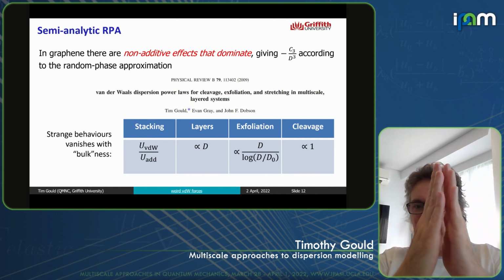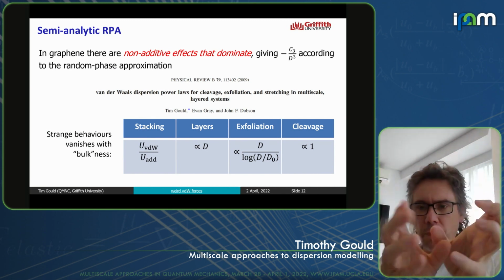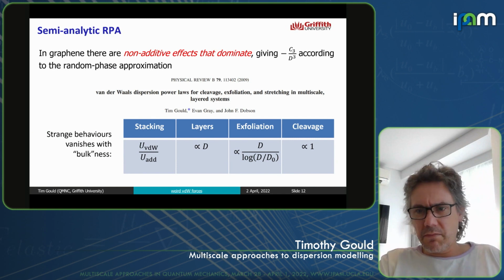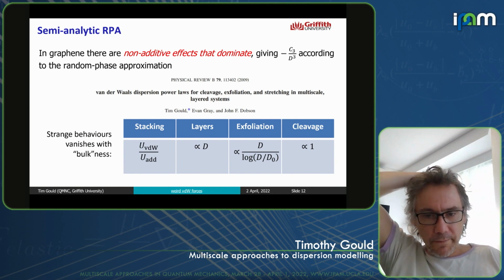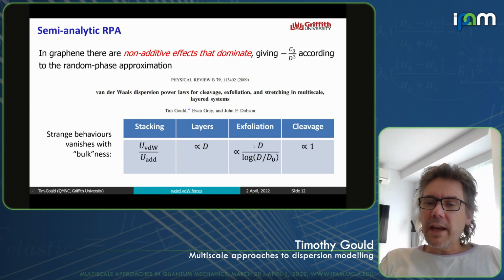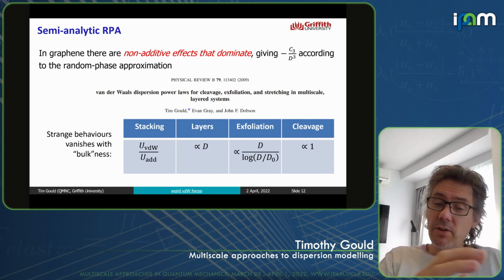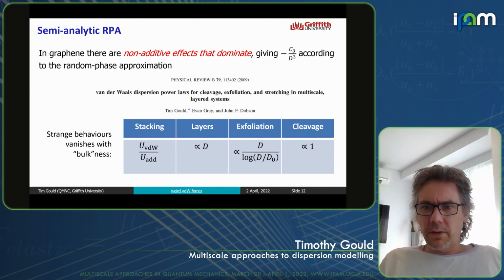So we've got a stack, if you imagine it like a stack of playing cards, basically. One way we can define it is we pull all our playing cards apart equally. We just take our playing cards and spread them out, and this is basically the same as a pair of layer problem. In fact, it's very close to what you'd get out of a pair of layer problem. Now, a second way we can define it is we've got our stack of cards, we peel off the top card. Now, this is not quite the same as stretching everything out. And there's a third way, where we don't peel off the top one, we split our deck of cards in the middle.